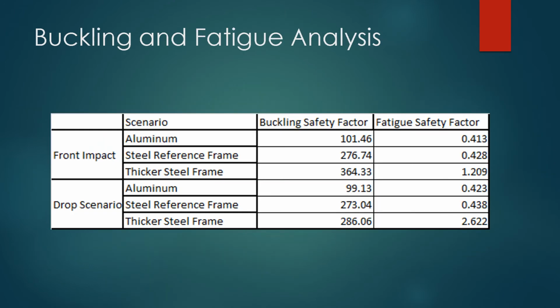Here are the results from the buckling and fatigue analysis. For this loading condition, the buckling safety factor was an adequate amount, with aluminum being the lowest and thicker steel being the highest. For the fatigue scenario, aluminum and the steel reference frame did not have infinite life, while the thicker steel for both loading conditions showed that it did have infinite life. For all these results, aluminum and the steel reference frame were pretty similar for each different scenario, front and drop.